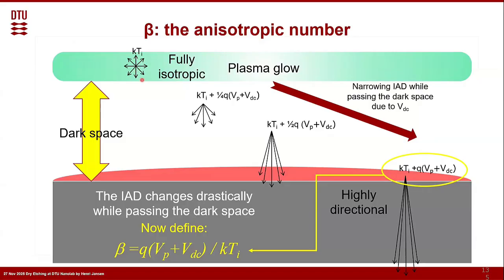But there are always a few of them who are passing by the boundary between the plasma glow and going into the dark space where the electric fields exist between the plasma and our wafer, which is located over here. Then, due to the electrical field, the ions are going to be getting a certain directionality. They are accelerated in this direction, downwards to the wafer, the normal direction. Of course, the ions still have the energy sideways, their original thermal energy. But the ones who are moving towards the wafer are accelerated by, let's say, if you are at a quarter of the dark space, a quarter times the charge of the ion times the potential difference between these two. When it's halfway, of course, it's halfway this energy coming in.